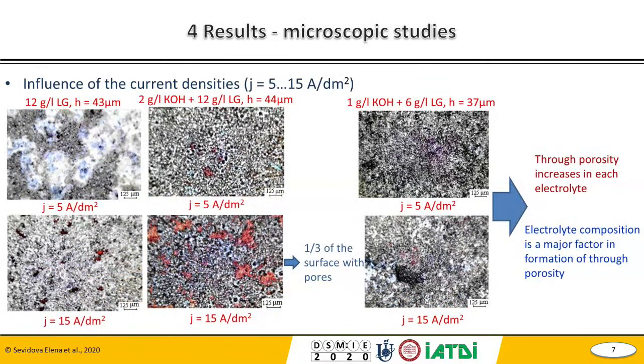It can be seen the influence of different current densities from 5 to 15, and it can also be seen that through porosity increases in each electrolyte, especially in our middle two slides, in electrolyte 12 to 2 to 12. And actually, electrolyte composition is a major factor in the formation of through porosity.